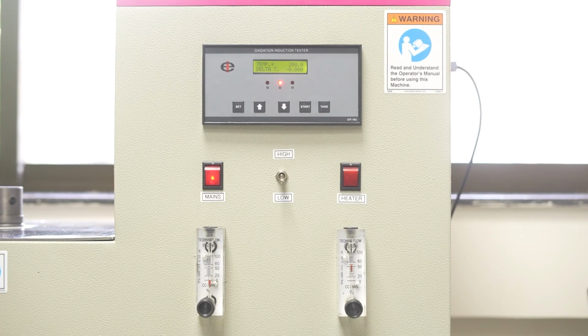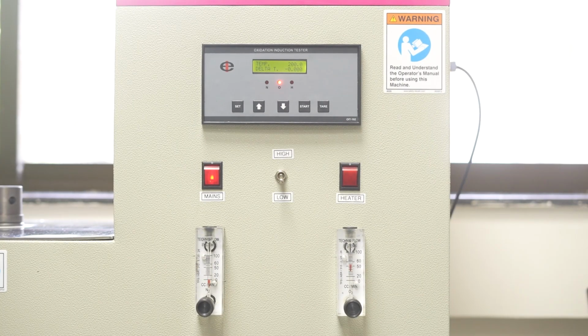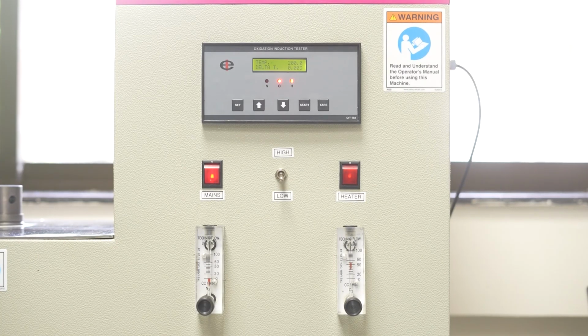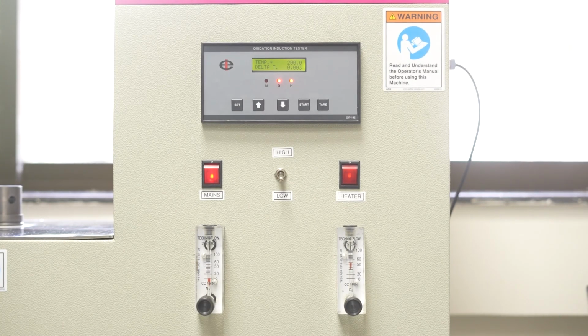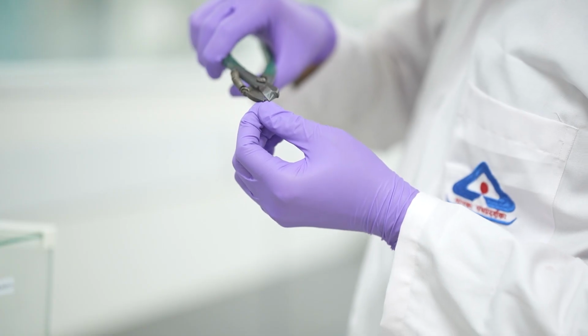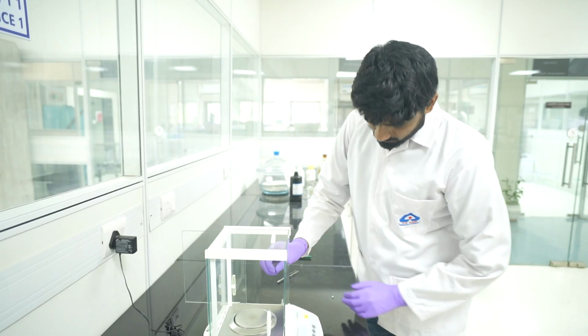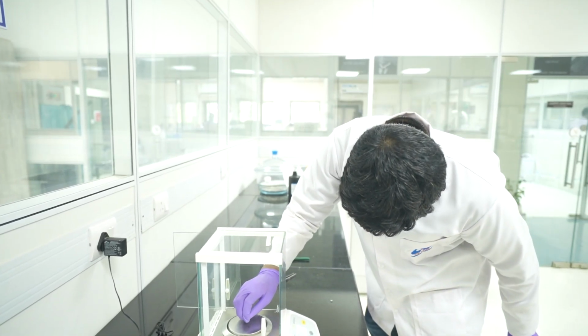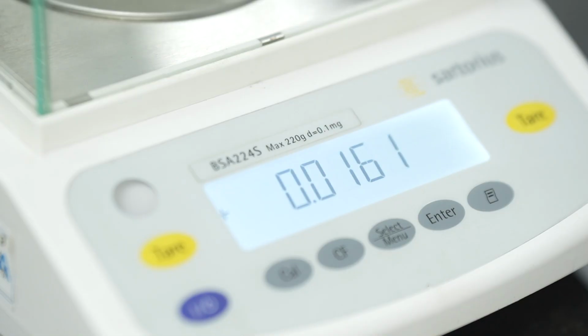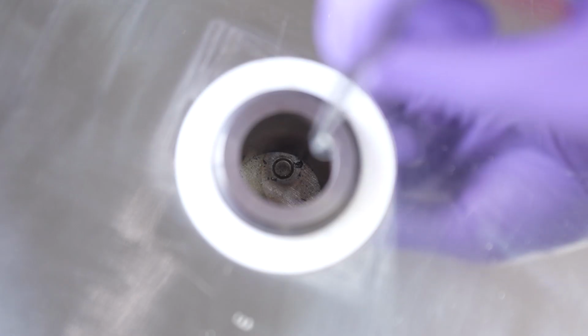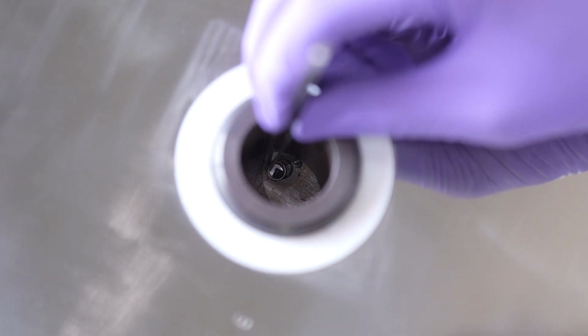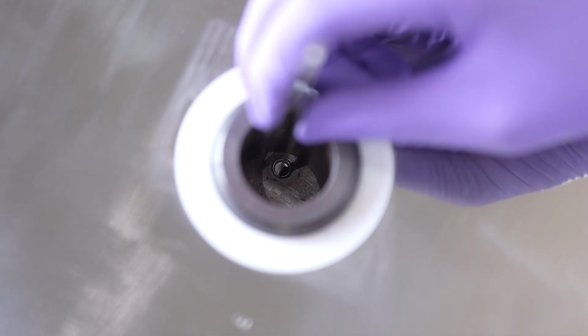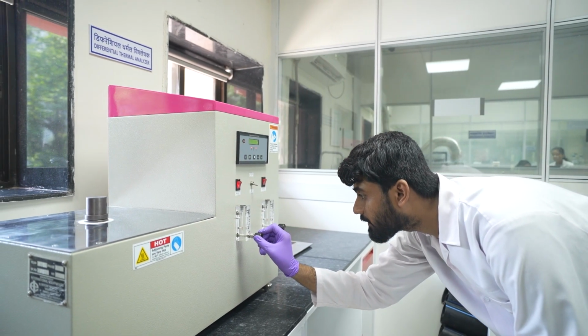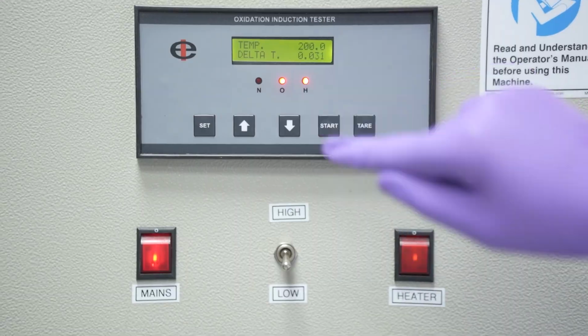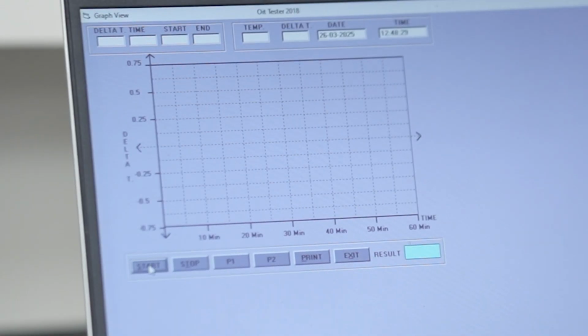The test is performed at 200 degrees Celsius under nitrogen followed by oxygen exposure. A core sample is extracted from the pipe, cut into 15 plus minus 0.5 mg discs from the inner, outer and mid-wall sections. The specimen is placed in an aluminium pan inside the DSC. For 5 minutes, under nitrogen, oxygen is introduced and the oxidation exotherm is recorded.